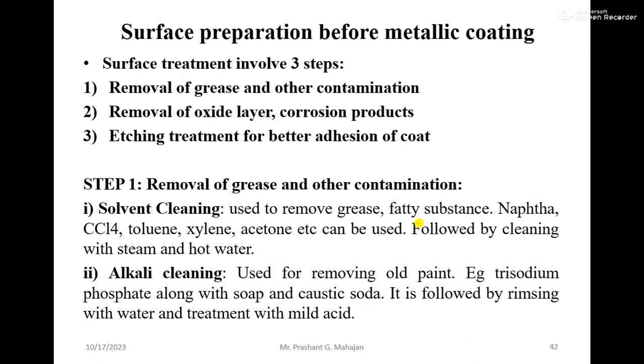The first step is removal of grease and other contaminants, which can be done by solvent cleaning followed by alkali cleaning. Solvent cleaning is used to remove grease and fatty substances — naphtha, CCl4, toluene, xylene, acetone, etc. can be used. This can be followed by cleaning with steam and hot water.